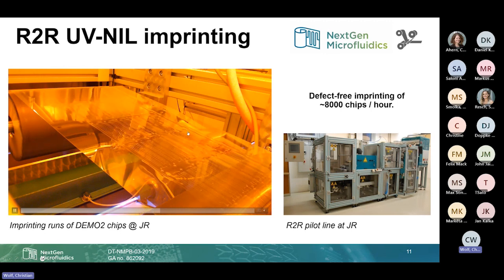Maybe you can even go higher than that. And one chip is 7.5 centimeters, and the web moves at approximately 2 meters per minute. So this sums up to around 8,000 chips per hour. So that's really, I would say, a high volume process. So the daily production with 2 8-hour shifts then sums up to something like around 130,000 chips. So that could be established very successfully. And here on the right-hand side, you can see a real image of this roll-to-roll pilot line installed at Joanneum Research.